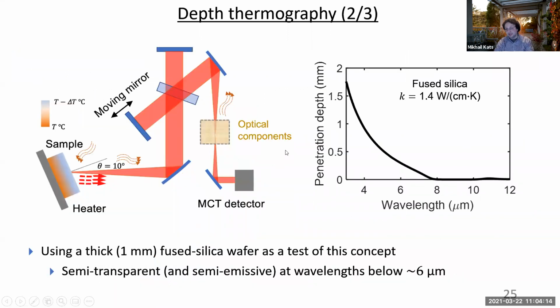So here is the test setup that we used. Again, we just used a simple FTIR setup with a sample sitting on top of the temperature stage. For our demonstration, we used this fused silica wafer that I was telling you about before, and the fused silica wafer is about 1 millimeter thick. It's convenient because, first of all, if you calculate the optical penetration depth, it's on the order of the thickness of our slab in wavelength ranges that we can measure with our spectrometer, and it also has a pretty low thermal conductivity, which means we're expecting a pretty significant temperature gradient to be established between the heater stage and the air fused silica surface over here, and so it should be easy to measure this. And so this is what we decided to use as our test sample.